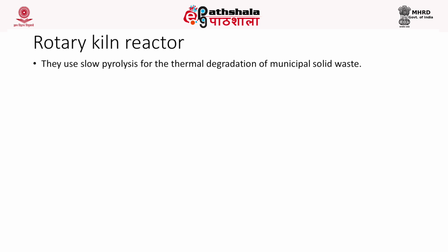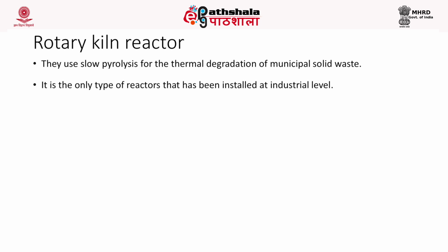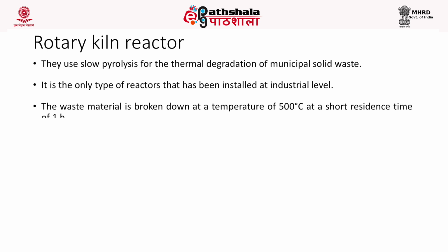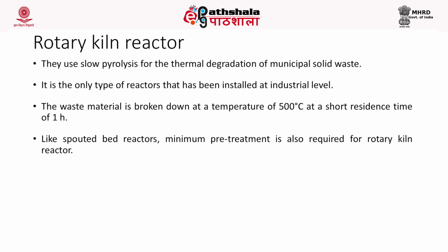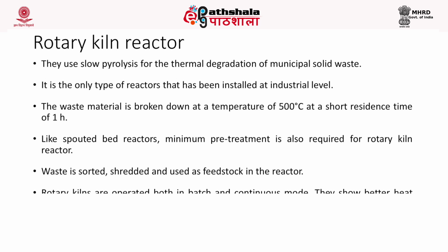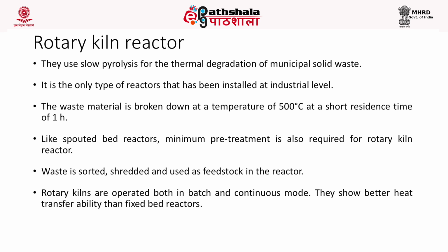The next type is the rotary kiln reactor. They use slow pyrolysis for the thermal degradation of municipal solid waste. It is the only type of reactor that can be used at an industrial level. The waste material is broken down at a temperature of 500 degrees Celsius at a residence time of 1 hour. Like the spouted bed reactors, minimum pre-treatment is also required for this type of reactor. That is, the waste should be sorted, shredded and used as a feedstock.